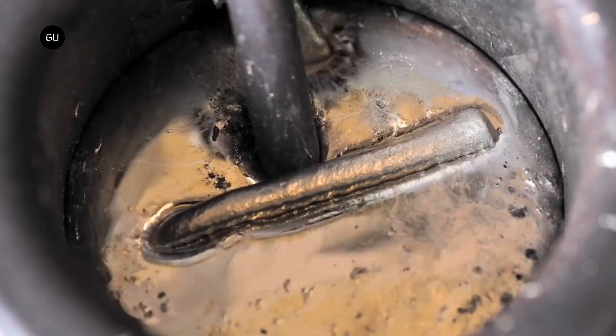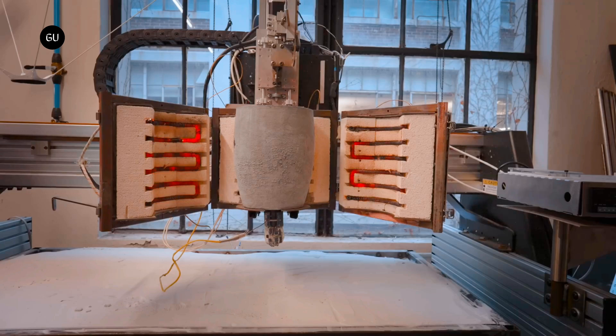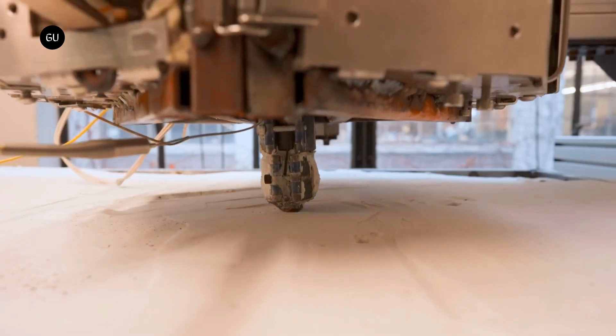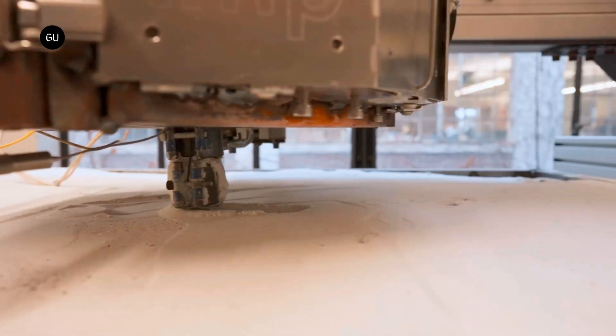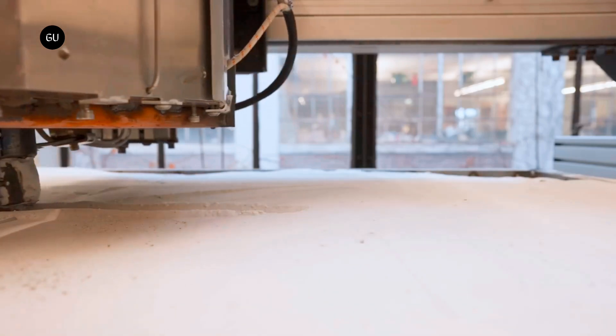Inspired by previous work with rubber, the research group first constructed a bread-loaf-sized electric furnace to heat aluminum beyond its melting point. The liquid metal is held within the machine's graphite crucible before being gravity-fed through a ceramic nozzle, and the molten metal is extruded onto a predetermined path formed on a print bed of 100-micron glass beads, where it hardens to form a 3D structure without needing supports.